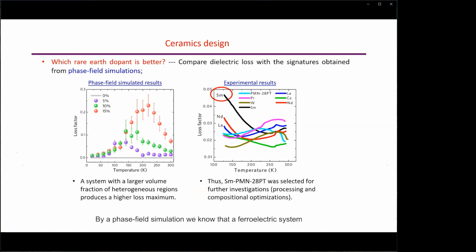By phase field simulation, we know that a ferroelectric system with a higher level of heterogeneity may produce a larger dielectric loss maximum. So we first fabricated PMN-28PT ceramics with different rare earth dopants, as shown here. Samarium doped PMN-28PT ceramics has the highest loss factor at a cryogenic temperature, so we focus our further studies on the processing and the composition optimization of samarium doped PMN-PT ceramics.